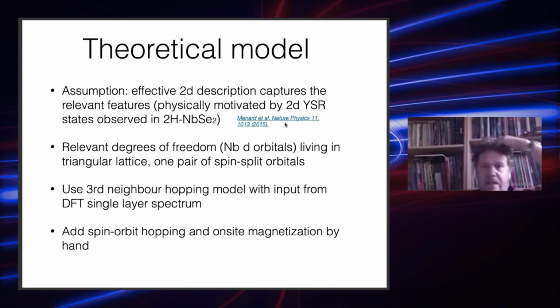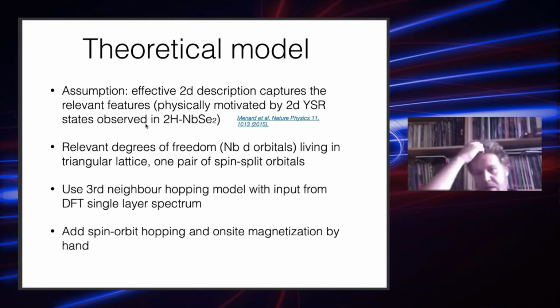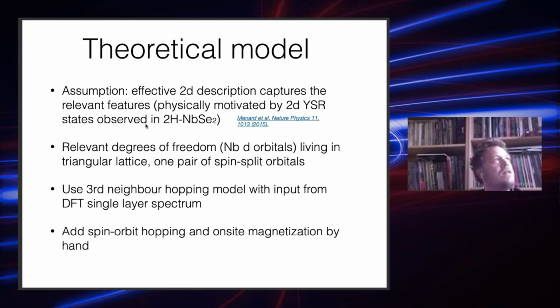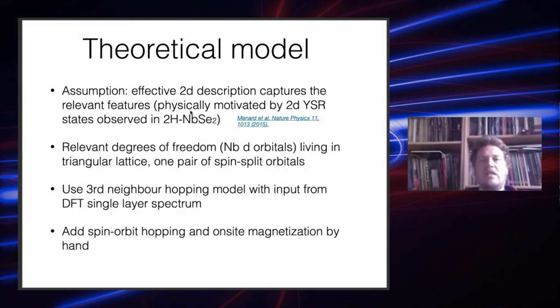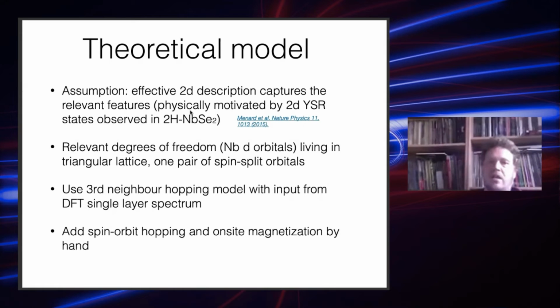Tribromide monolayer. And this is motivated by the fact that you can actually observe these 2D YSR states, as Pascal mentioned in his talk, so that for many purposes, at least for the purposes of individual YSR states, 2H niobium diselenide, which is actually a 3D material, behaves very much like a 2D material. So this is our physical argumentation why this 2D description is a very logical starting point.